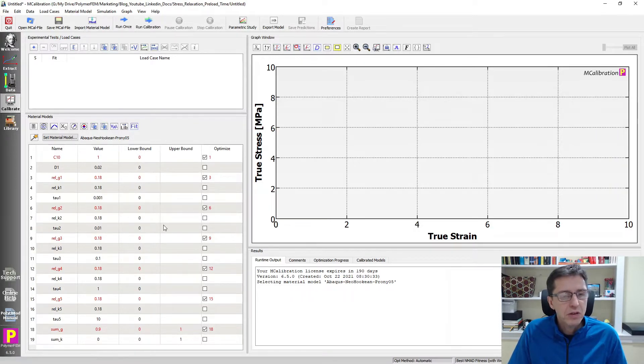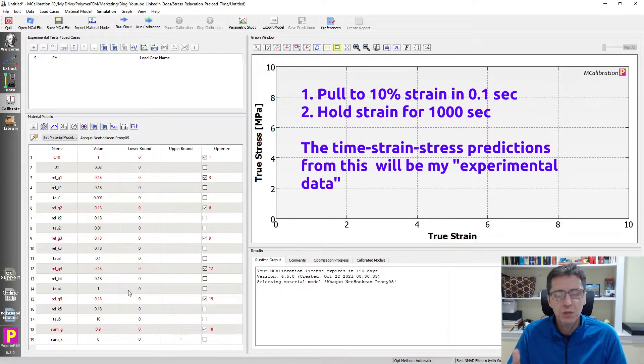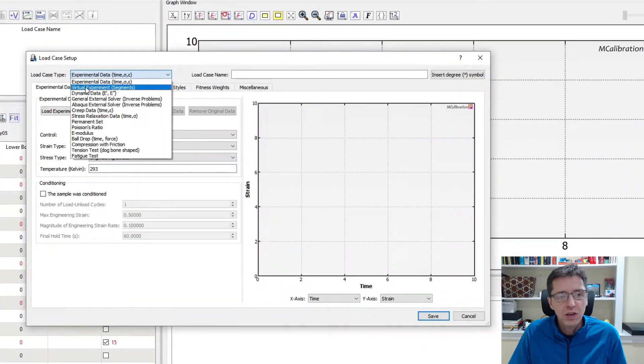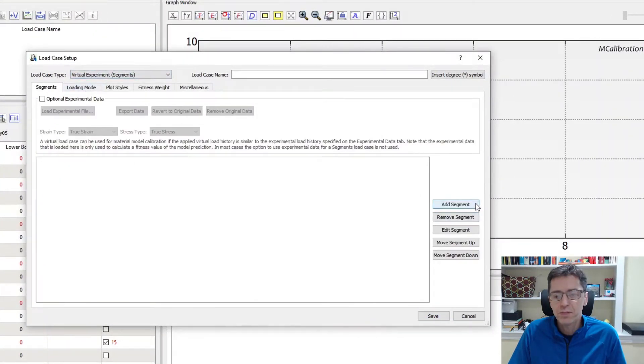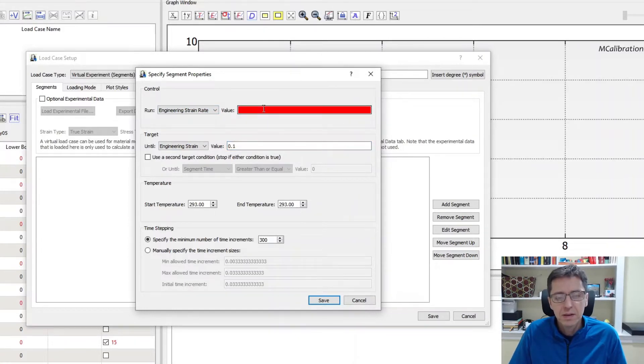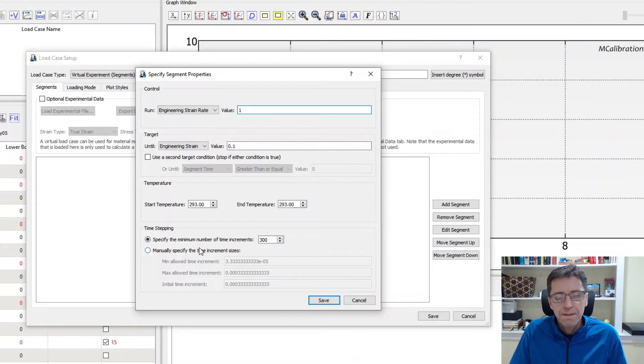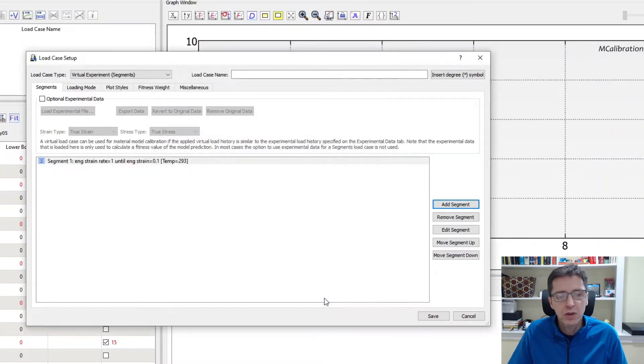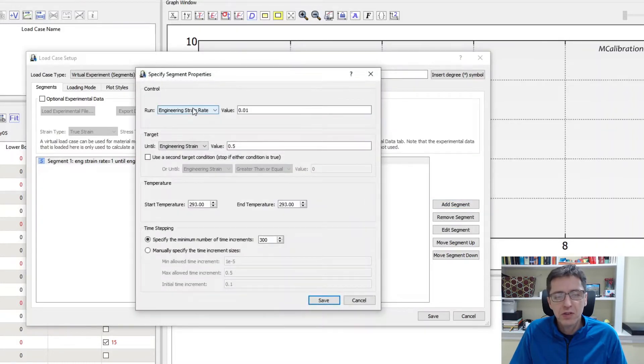Here are the parameters selected by the software. What I'm going to do is figure out how this particular material model will behave if I pull on it to 10% strain in 0.1 seconds and then hold the strain constant. One way to do that is to create a virtual load case - I don't have actual experimental data, so I create a virtual load case. I'm going to use an engineering strain of 10% and pull it to that in 0.1 seconds, giving a strain rate of one. That's the first step - it's loaded to 10% strain. Then I'm going to add another segment: this is the stress relaxation segment that I want to study.